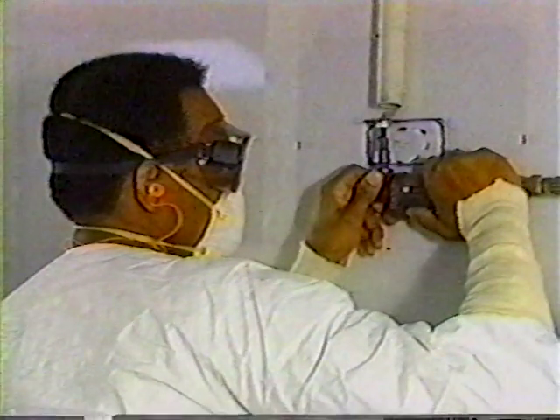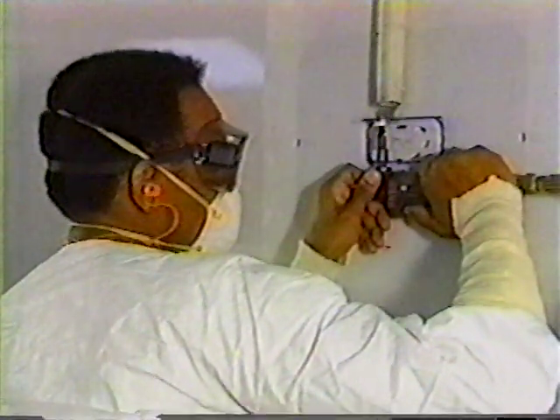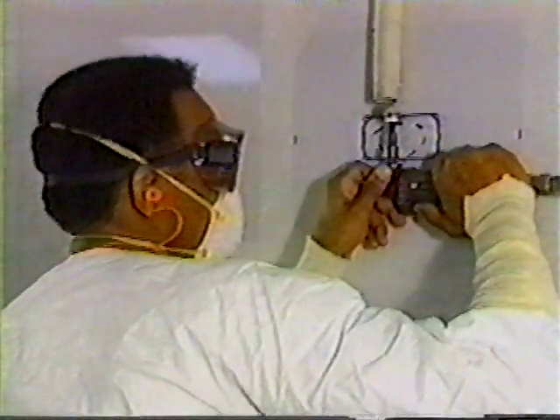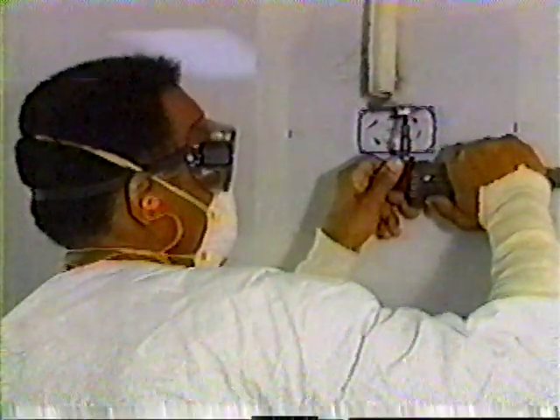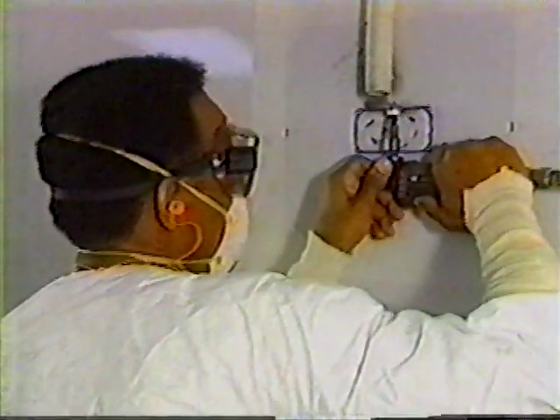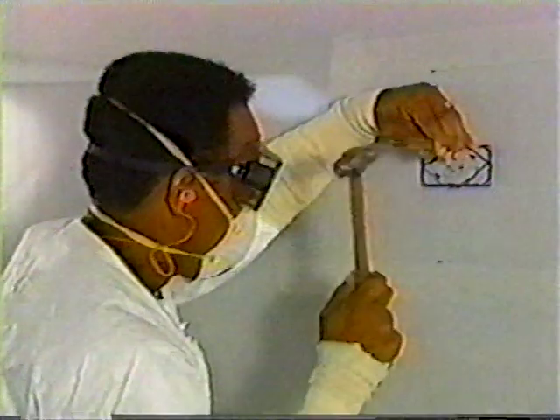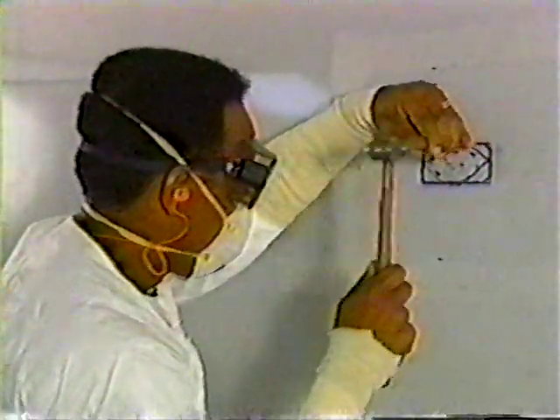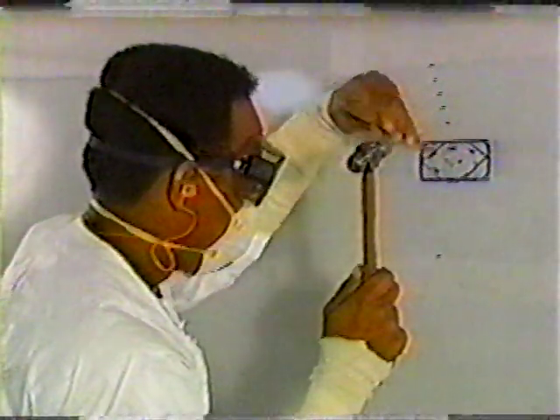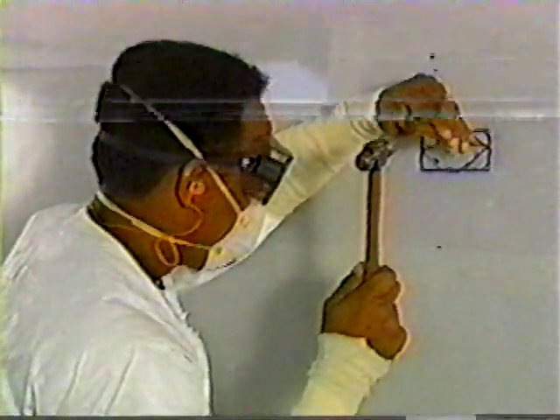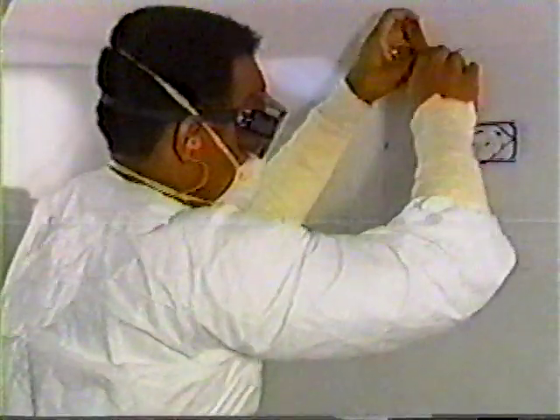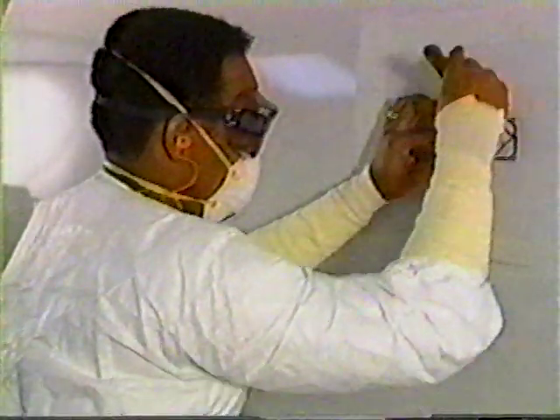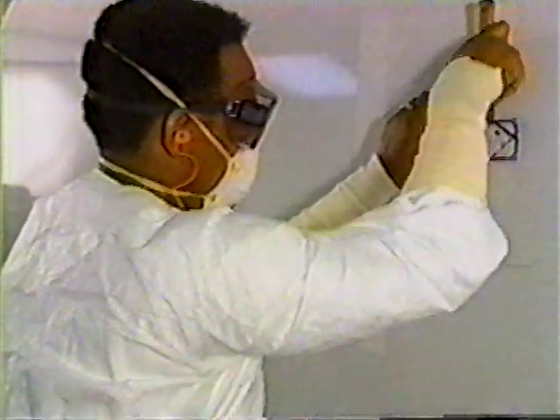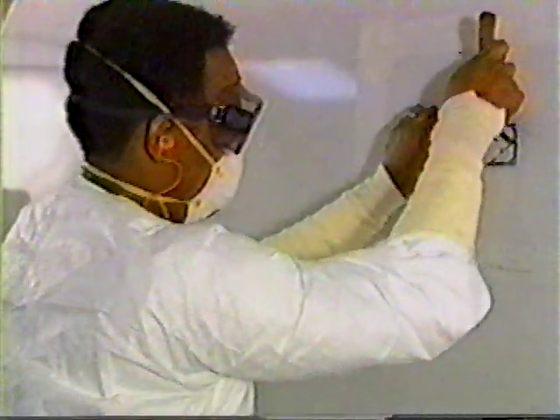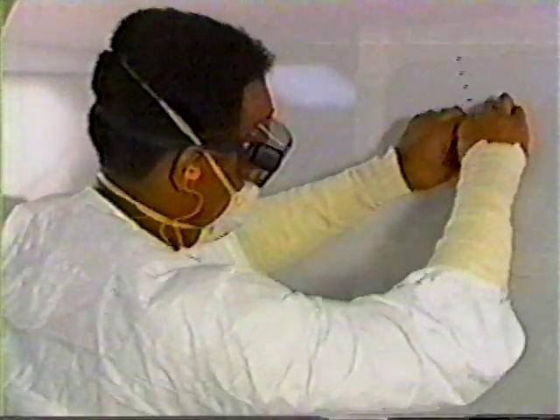Next, begin removing the delaminated material by carefully cutting the panel with a radiac blade around the area marked for the repair. To complete separating the core from the rear panel, use a hammer and putty knife to gently cut the remaining core. Then, carefully remove the outer skin and damaged core from the repair area, making certain the composite panel on the opposite side is not damaged.